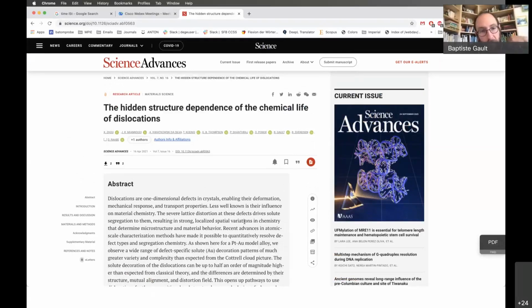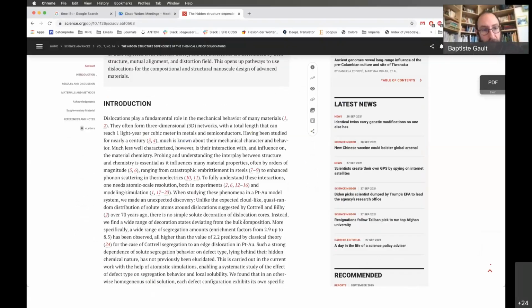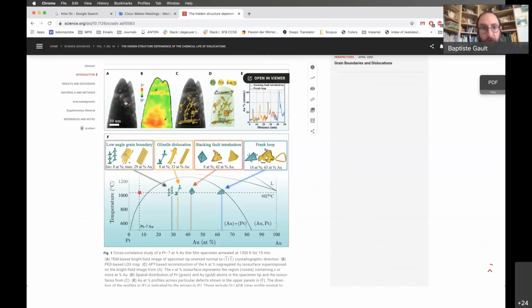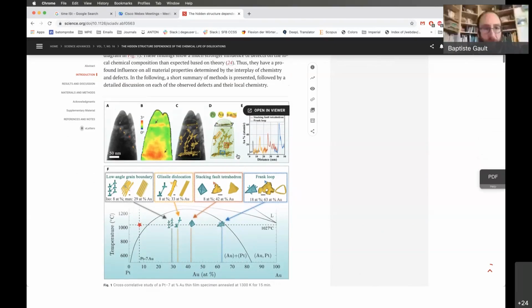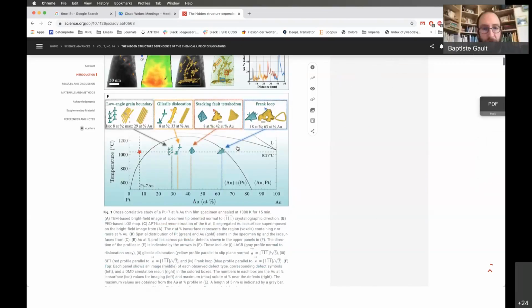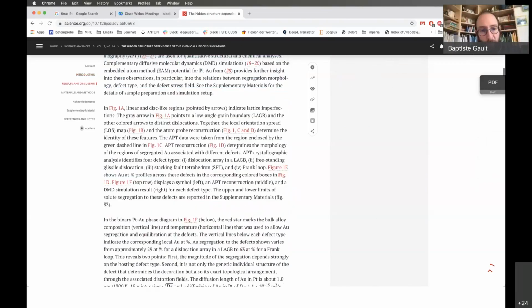What Wright did was look at thin films, platinum gold, that have been peeled off from the substrate, so they're highly deformed, and then heat treated to induce segregation to the dislocations that have been formed. It's one of the systems that actually has a big miscibility gap. So the plan was to also see how solutes would distribute along some of the dislocations and defects and so on and so forth. Wright did some pretty TEM and then some atom probe.